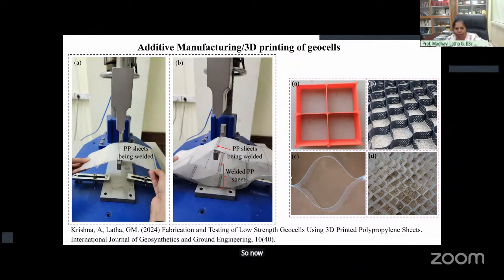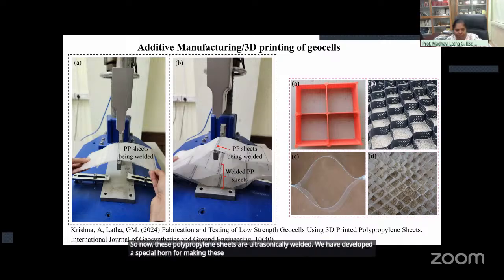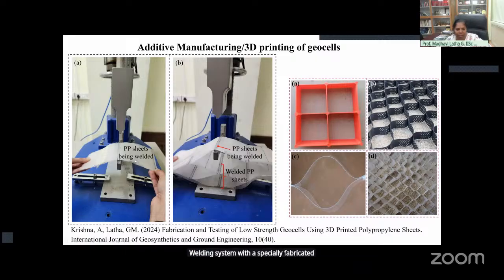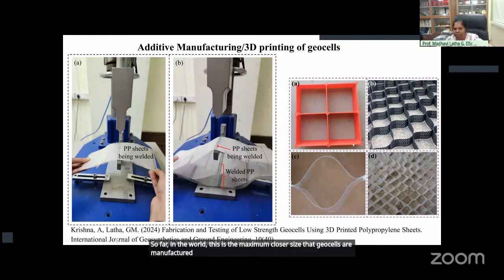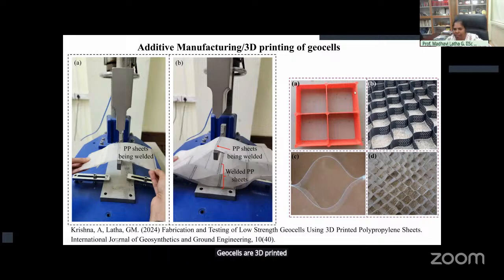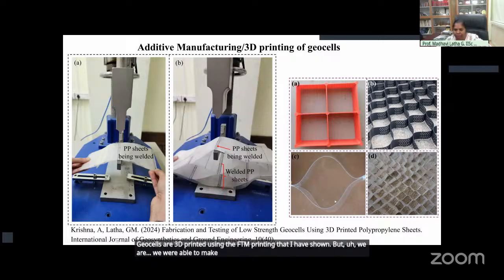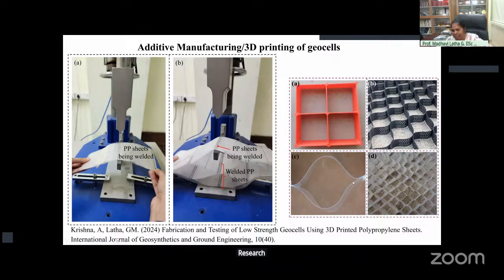So now these polypropylene sheets are ultrasonically welded. We have developed a special horn for making these geocells within our lab. This is the ultrasonic welding system with a specially fabricated horn where we can weld the PP sheets. So far in the world, this is the maximum closer size that geocells are manufactured. This box type of geocells are 3D printed using the FDM printing that I have shown. But we were able to make the exact polymeric shape. I mean, now we have moved from making polypropylene sheet and ultrasonic welding to directly printing the geocells. This is very recent research that is yet to be published.